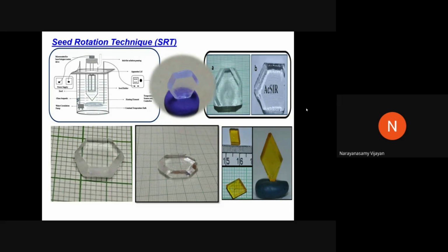So we developed our own seed rotation technique. We made a seed platform, put one small seed crystal on it, and poured the same saturated solution. Because of the bidirectional rotation, clockwise as well as anti-clockwise, the concentration throughout the solution is uniform, so I can grow very good quality single crystals. If you compare with the market rate, 5 mm by 5 mm crystals are sold outside for approximately a few $100s. These are some of the organic single crystals and semi-metal organic single crystals. But we can grow them with very inexpensive equipment using slow evaporation or the seed rotation technique.